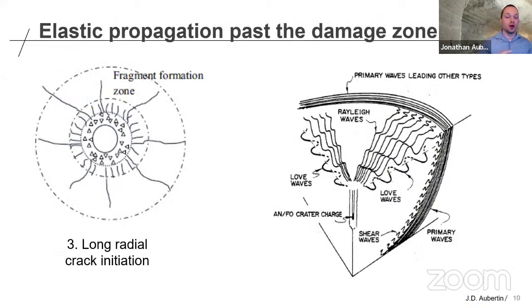Past this damage zone, what you have is the propagation of an elastic wave. Basically, you've damaged the rock mass near the blast hole, you've generated a series of radial fractures. Then past this, you have elastic transmission and propagation of pressure waves. The primary pressure wave that we usually talk about is the P wave, the compressive wave. That's usually the driving shock wave that is of interest for blasting. You have all the other types of seismic waves that we're used to, especially shear waves whenever you interact with some heterogeneous components, some fractures, some local inconsistency. But the P wave is typically the driving factor of interest.